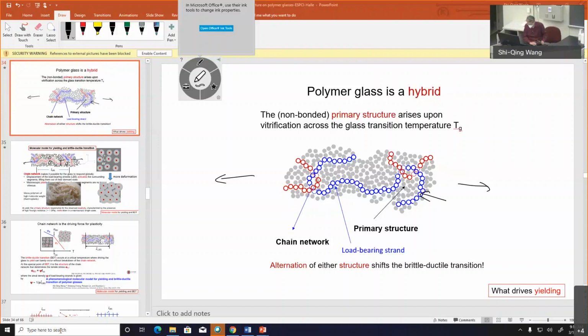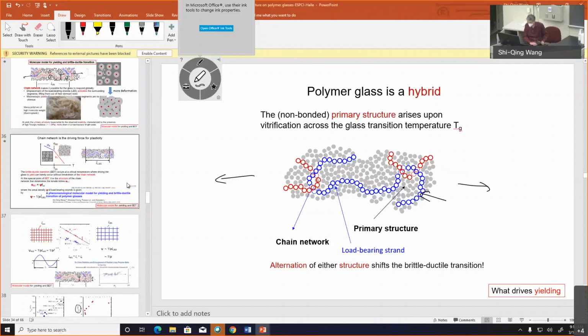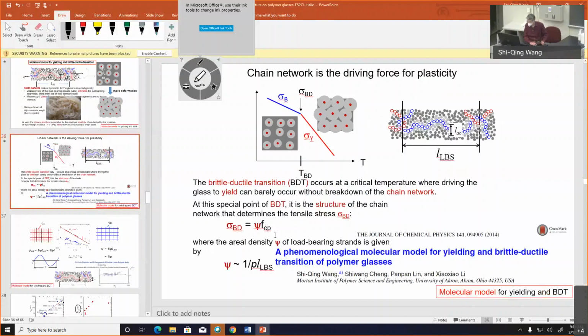Then this condition of failure will be reached across this 10 million layers. Maybe the 100th layer will reach that condition first. And that's enough, because that's the place that will break. That's why you see this thing breaking so sharply. In other words, once I have this breaking, what happened to the rest? Totally intact. By definition, nothing happened. They remain as strong.